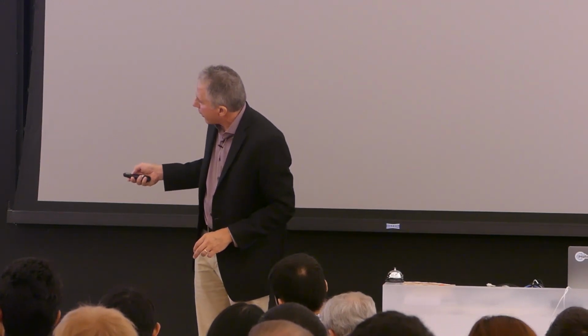So this is what the luminescent solar concentrator looked like. Remember I said that you could literally see the glow. For the luminescence of the cadmium selenide quantum dots, they glow in the orange, and so you see orange light emanating from the edge of the concentrator. You don't see it coming out the top. That's because we have these light trapping mirrors on the top that are enabling relatively high concentration factors.